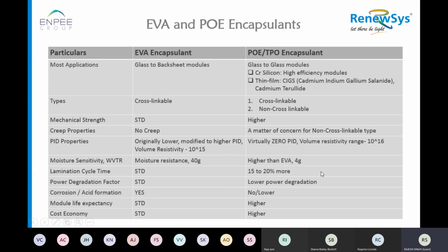The only drawback of POE is that it takes a little more time in lamination. Generally, it is glass to glass which is used for this, and it takes a little bit longer time to penetrate heat through two sides of glass. And it is less corrosive. It is higher in module expectancy because it does not create any chemicals, and it does not create acetic acid, because POE is neutral, or we can say a non-polar material, whereas EVA has acetic acid formation because of the presence of vinyl acetate, as we discussed before.